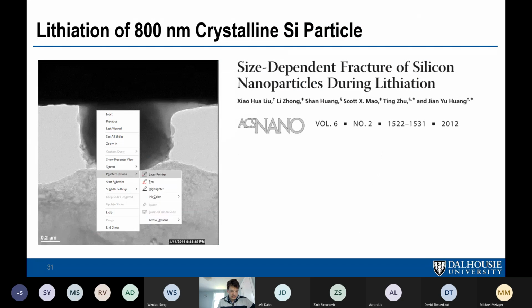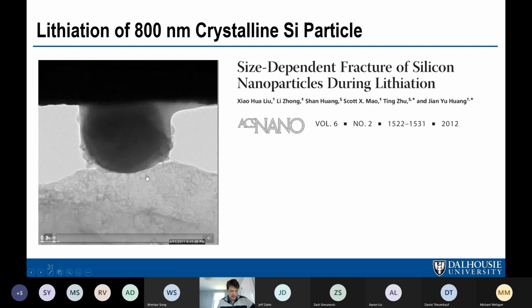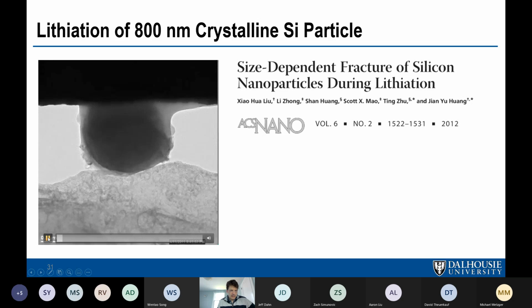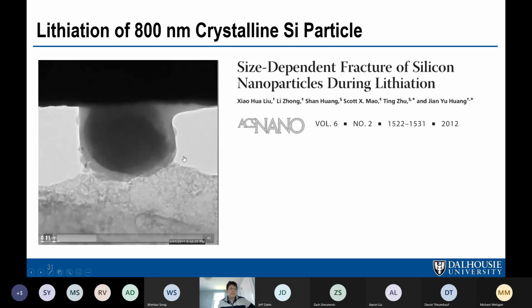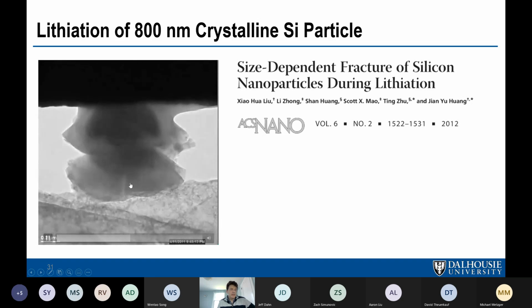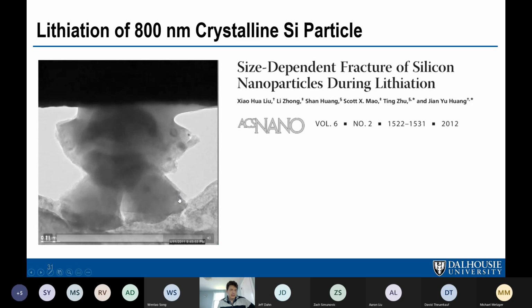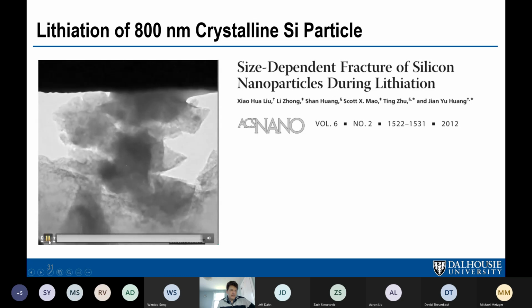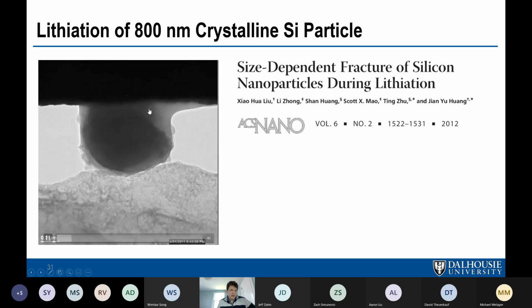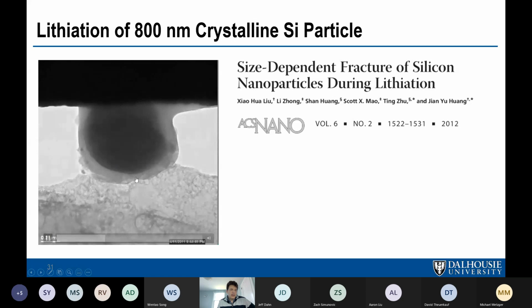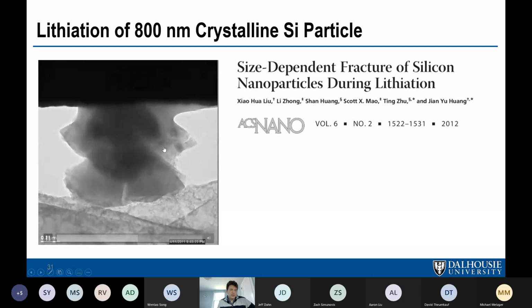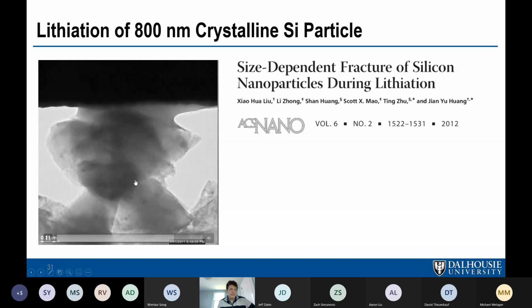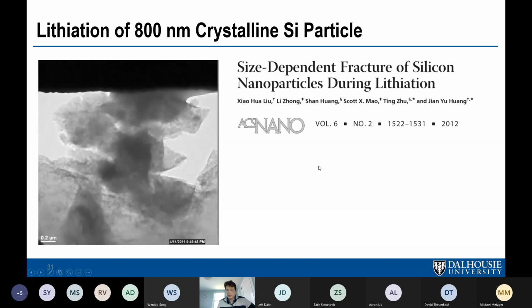Maybe I need to get my pointer away to get this movie to work. Here we go. So this is a TEM picture of a piece of silicon particle being lithiated. I'll play it again. You can clearly see the core shrinking, and then this phase of lithiated amorphous silicon forms around it, and it just falls apart because of all the stress on the particle.